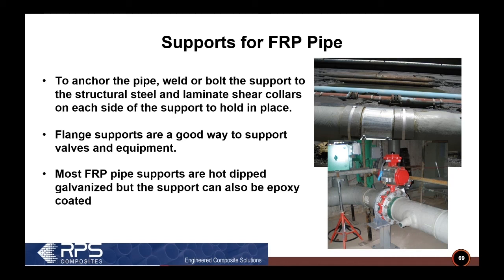You can use a flange support to pick up a flanged heavy weight like this valve that's shown in the bottom picture. And you'll notice it's a nice idea to use a flange support because, for example, the T that's coming out on the right-hand side of the photo has a hub, a repad, that's going to interfere with a typical trunnion type of support or a pipe clamp. So the flange support is a nice way to pick up equipment. And generally speaking, I call them FRP pipe supports, but the pipe supports themselves are generally hot dip galvanized steel. They can be epoxy coated, but generally they're hot dip galvanized.